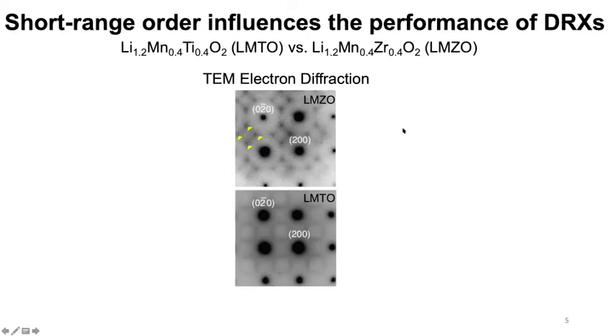Electron diffraction can be a useful tool to characterize the short-range order in DRX materials. As we can see from the two electron diffraction images shown here, the round spots represent the long-range order feature, and we can see both materials demonstrate the same long-range ordering.